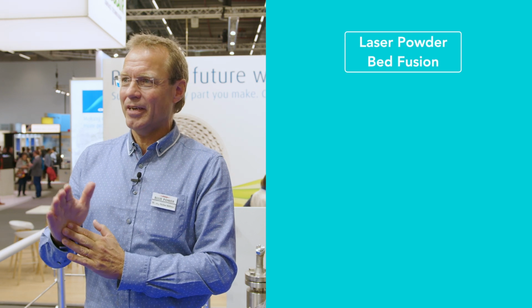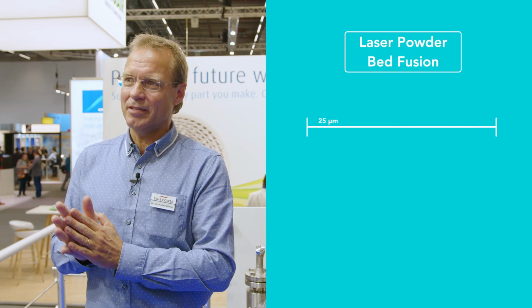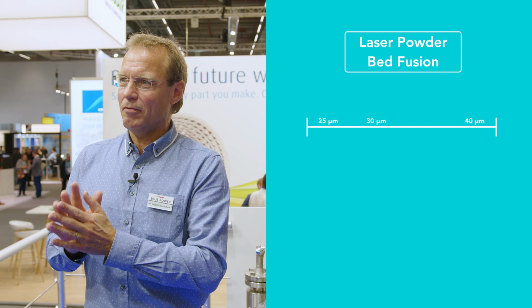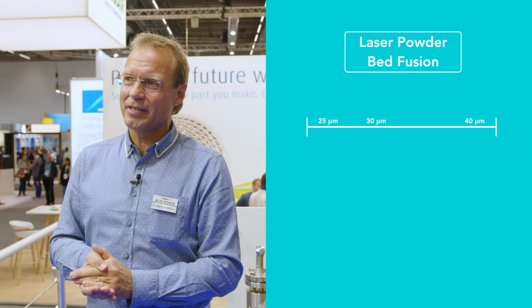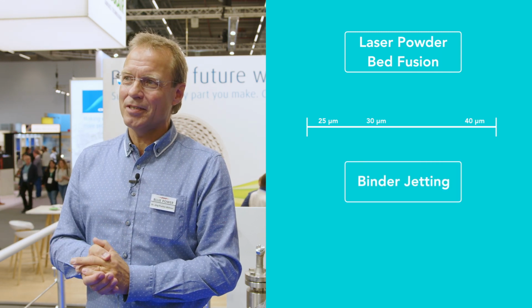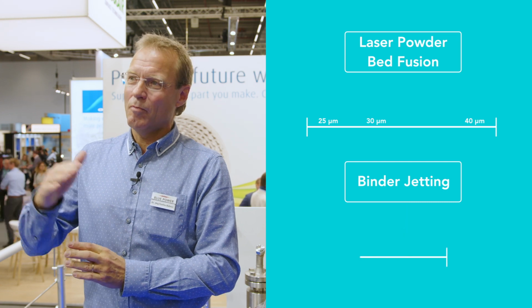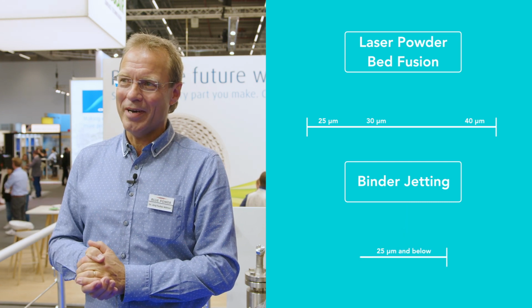For platinum, we so far have worked on powders for laser powder bed fusion and binder jetting. So for laser powder bed fusion, we are targeting an average particle size around 25, 30, 40 micron depending on the printers. And for the binder jetting processes, we look at particle sizes more below 25 micron. So the nice thing with gas atomization again is that you can atomize into these size ranges.